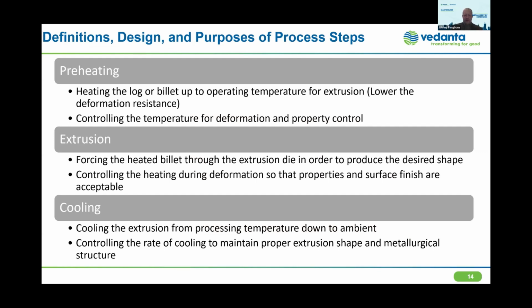So looking more specifically at the extrusion process itself, we have our preheating step where we're going up to that critical temperature range. Of course, we need to do that. We need to have a softer alloy that we can push through the die and do that reliably. But we also need to control it in a way that we get the final product that we want. And in light of what we're talking about, particularly the property control or mechanical properties that we need, by controlling how we go through that critical temperature range.